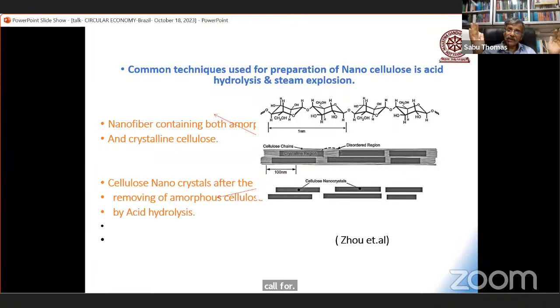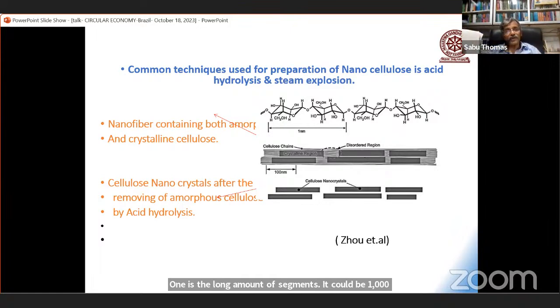Dear students, when you start from plant fibers and do steam explosion and acid hydrolysis, we are able to get two products. One is the long nanocellulose. It could be 1,000 nanometer in length. The diameter could be in the range of 20 to 70 nanometer. This is the long nanocellulose where crystalline and amorphous phases coexist.